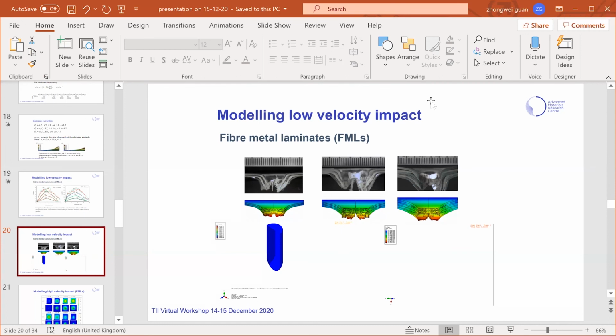Okay, and do you do experimental tests to extract the strength and stiffness for the cohesive bonds? That's a good question. We have some quasi-static material data, but testing under impact or blast events to get interface properties is extremely difficult. So we used inverse modeling. Based on the quasi-static data, we use inverse modeling to identify those parameters, stiffness and strength, in the normal and the two shear directions. Okay, thank you, Dr. Guan.